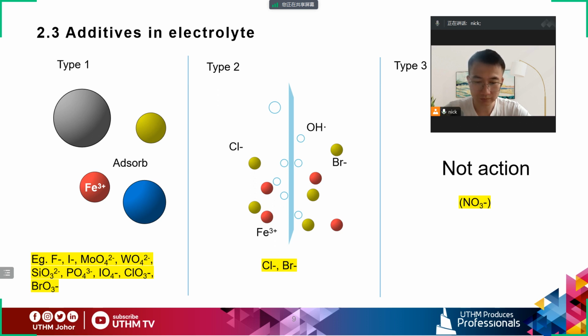Some additives can also facilitate the production of hydroxyl radicals in alkaline conditions. However, under acid conditions, it reacts rapidly with electron-donating groups. There is yet a type of electrolytic ion that does not react with hydroxyl radicals and remains inert during the electro-oxidation process.